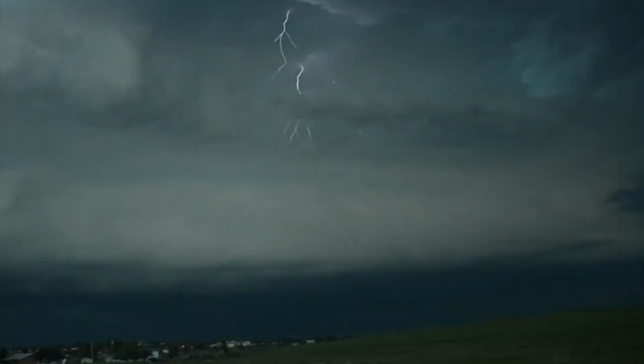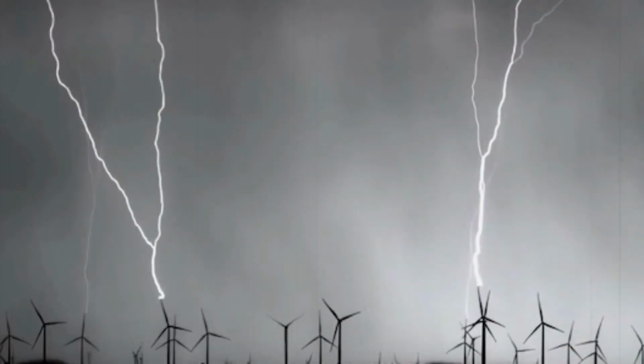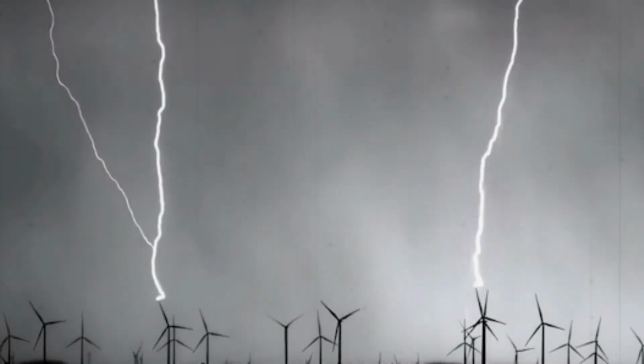Left untreated, the damage grows deeper, eventually exposing composite layers and leading to delamination. Another serious issue is lightning strikes. While blades are built with internal lightning protection systems, usually metal conductors running down their length, a direct strike can still burn through the gel coat, create holes, and sometimes even cause internal delamination. Damage isn't always obvious. That's why ultrasound and thermography tools are essential for detection.